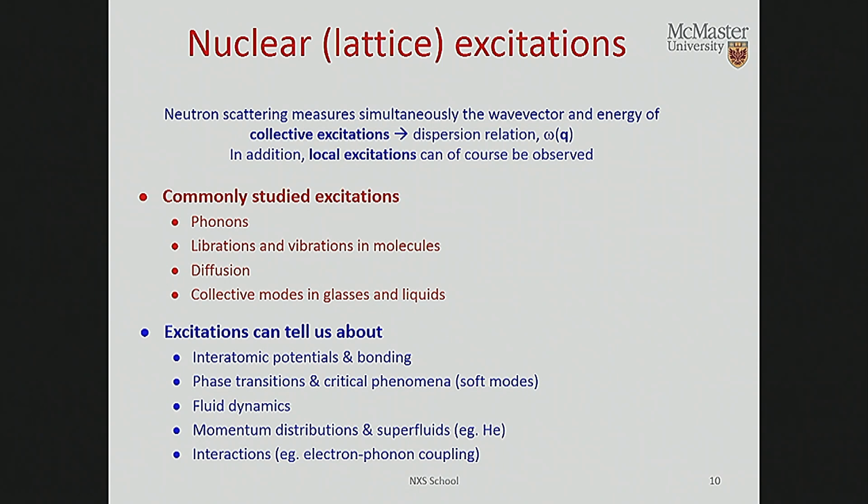And so you might be interested in understanding these for general reasons, or you might want to understand the details of the interatomic potentials, because if you can understand the details of the energy versus momentum dispersion relations that describe, say, the phonons, then what you're really understanding is the nature of the interatomic forces that are at play in the solid, okay? So you can understand the interatomic potential, which really means understanding the Hamiltonian of your sample at a very microscopic level, okay?